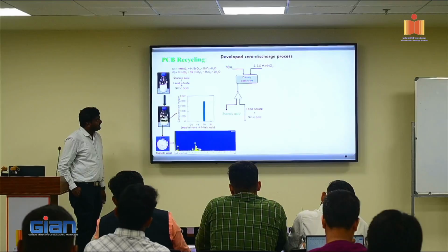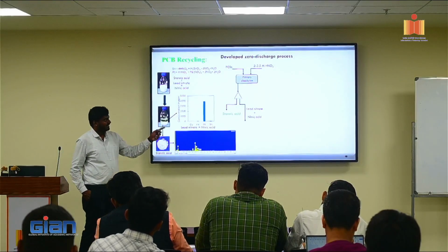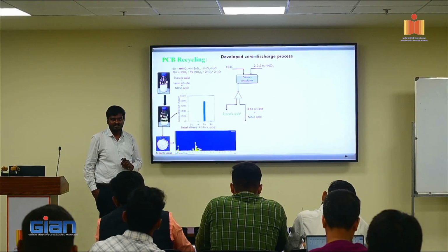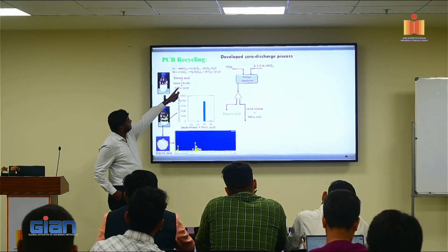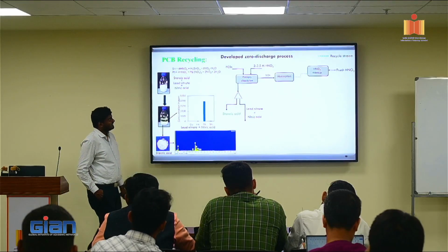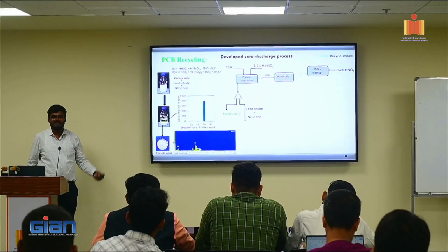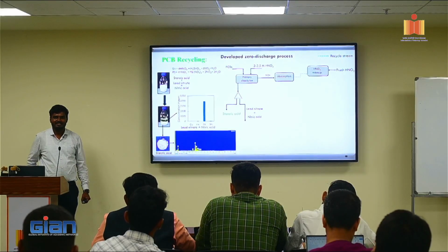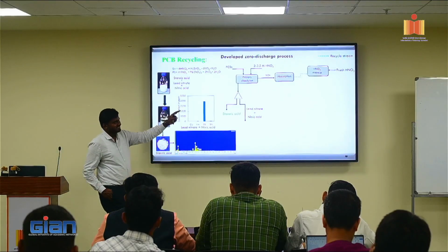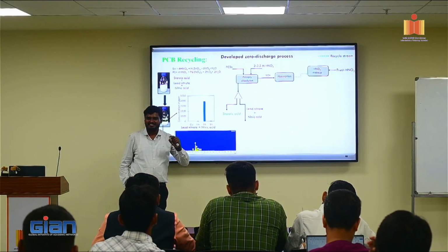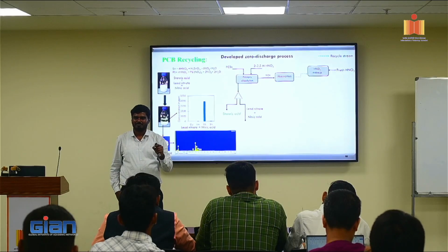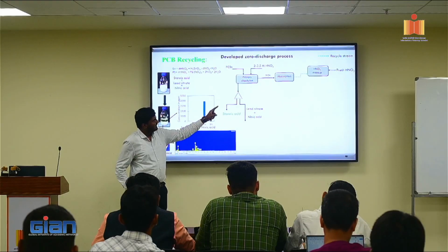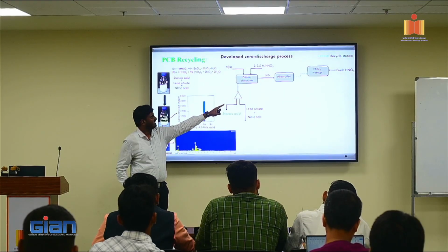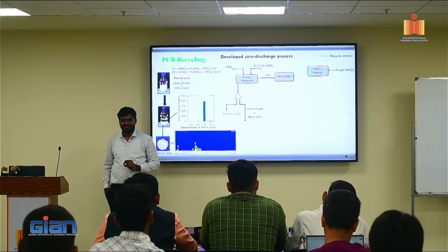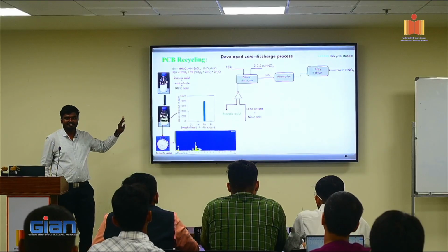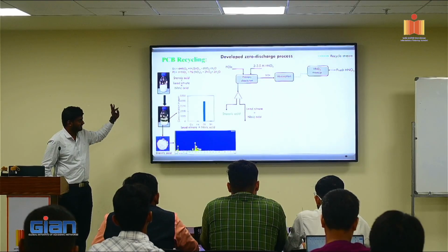So after doing this, I separated stannic acid, one product, green color one, and I have a solution of lead nitrate and nitric acid. Meanwhile, parallelly there is NO2 gas. This NO2 gas, I wanted to absorb. Basically, if you dissolve NO2 in water, it forms nitric acid. But when you see the stream, that blue color line that is coming, the concentration of nitric acid is very low there, like 0.01 or 0.005 molar. I'll take that and mix it with fresh acid and reuse it for primary dissolution. That was the ideology. So now NOx gas is not released into the environment. I will show you the reactor design also in some time.